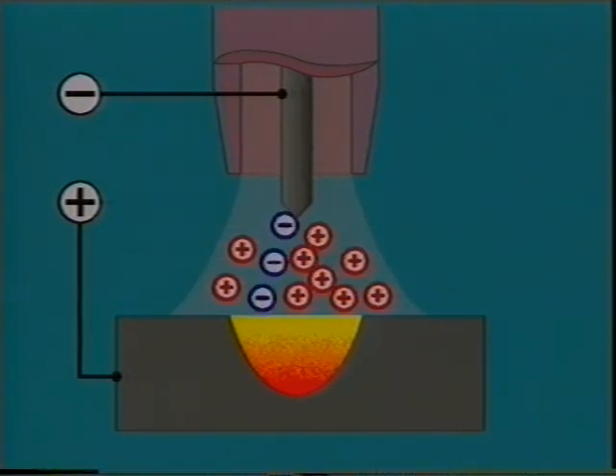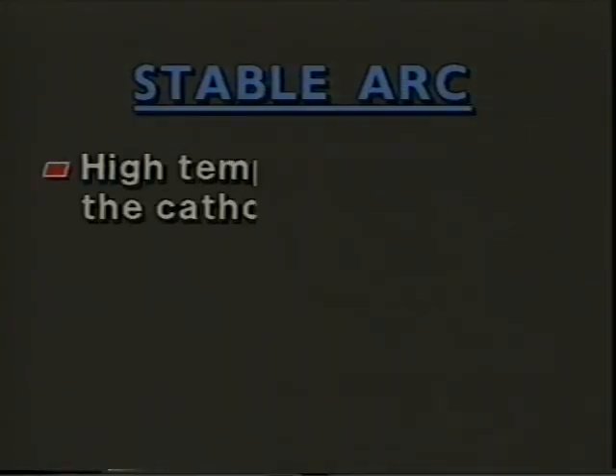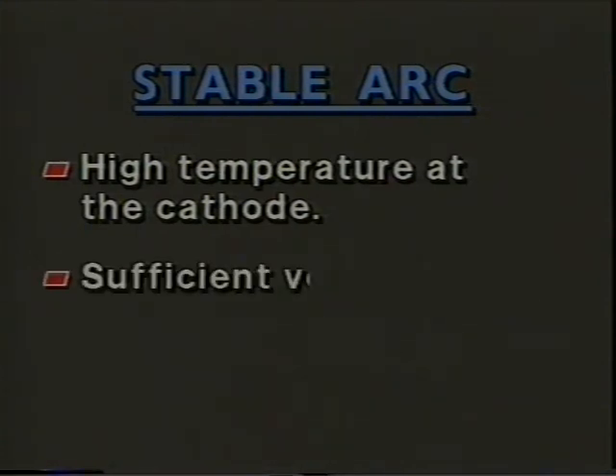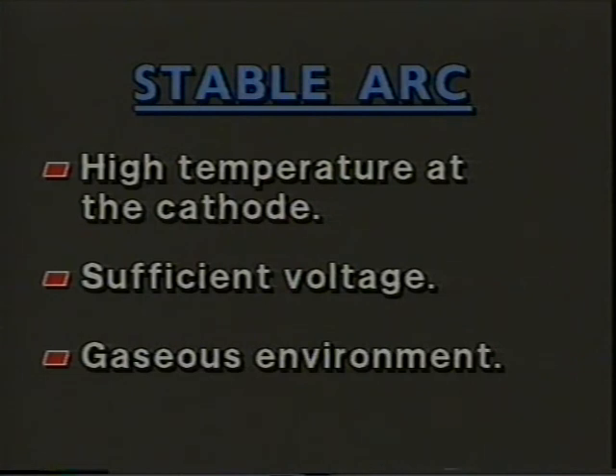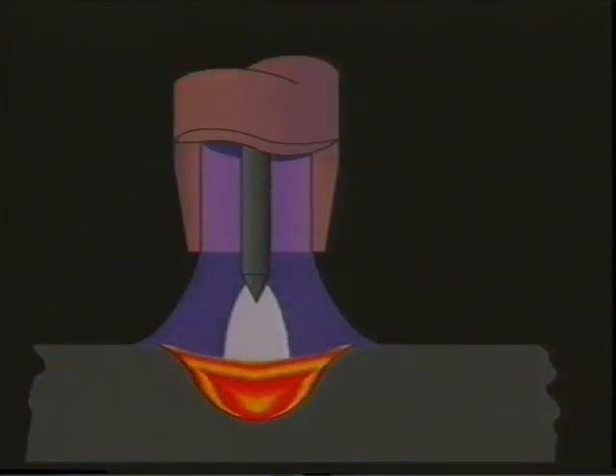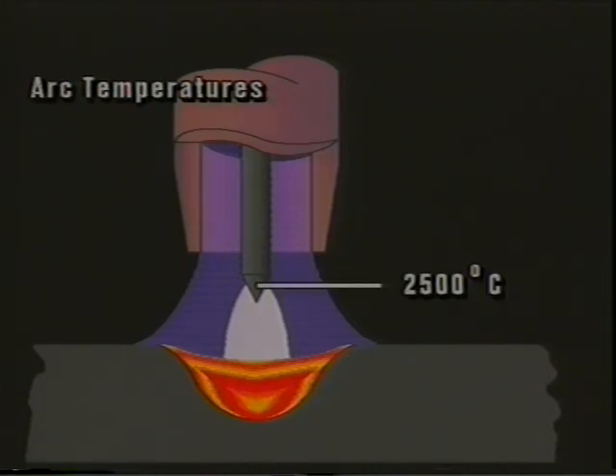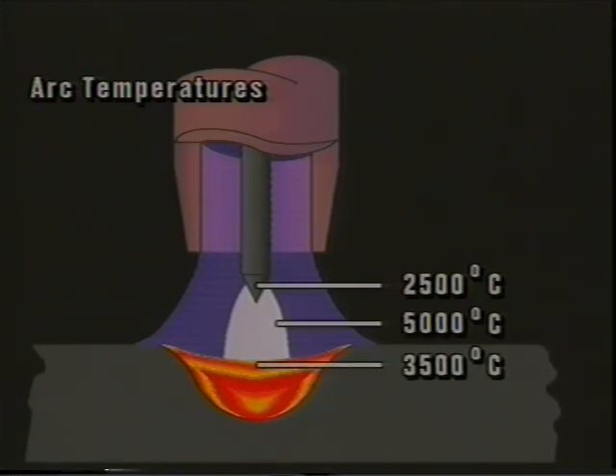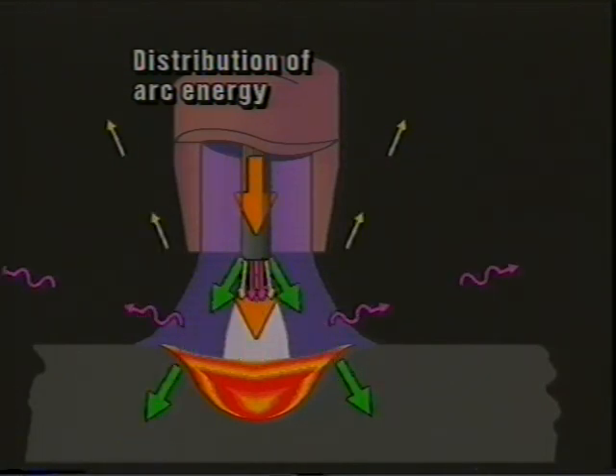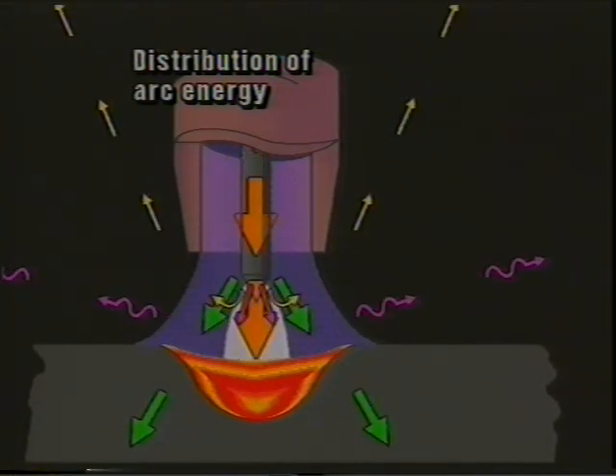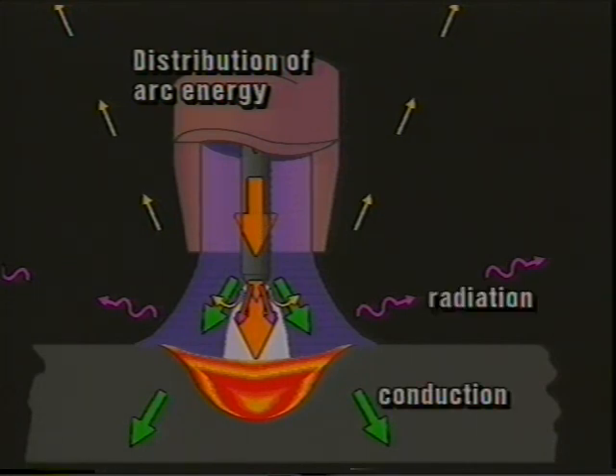The ionized gas increases the electric field, accelerating the electron avalanche. To support a stable arc, we need a high temperature at the cathode, sufficient voltage higher than the ionization potential of the gas, and a gaseous environment providing sufficient positive ions. The temperatures in the arc vary and are typically 2,500 degrees Celsius at the cathode, 3,500 degrees Celsius at the anode, and 5,000 degrees Celsius in the arc column. Only about 40% of the arc energy is actually used in welding. The rest is lost by conduction into the workpiece, by radiation, by convection with the shielding gas.